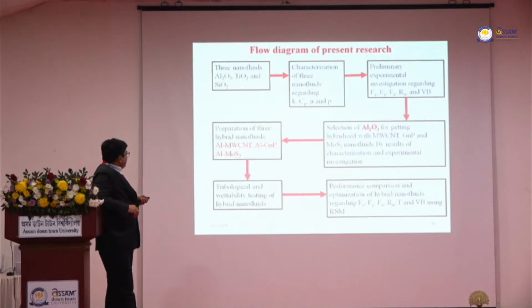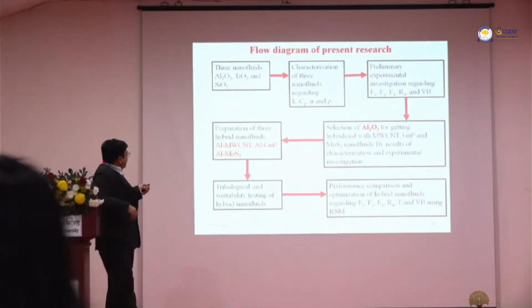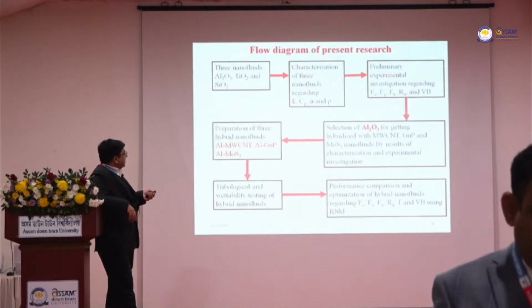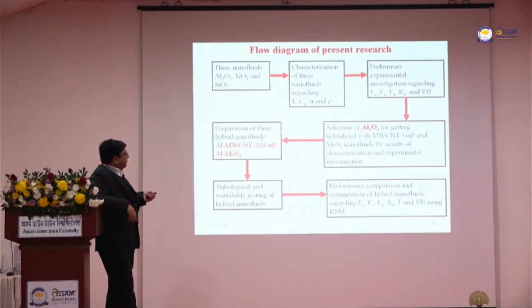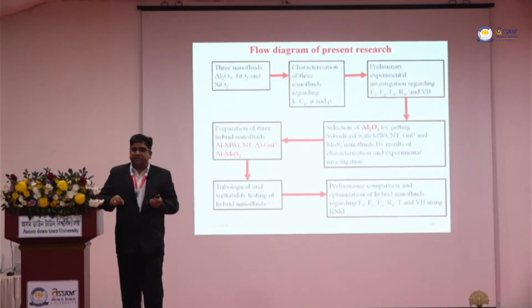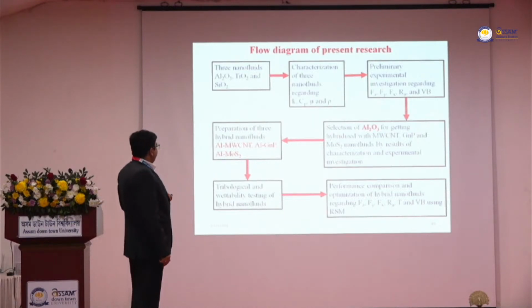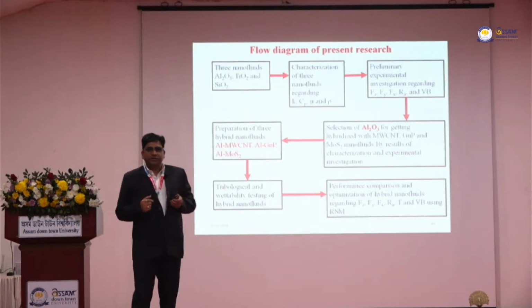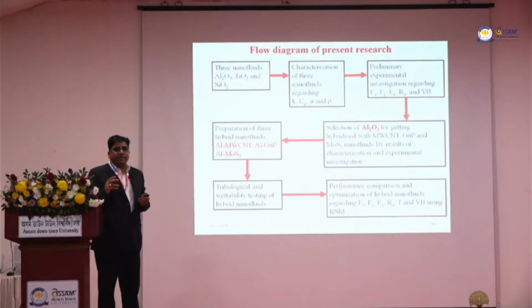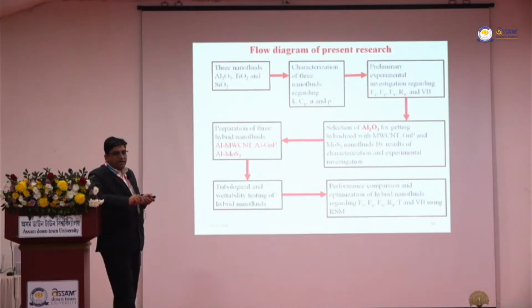Then we did the characterization of the 3 nanofluids: what their properties are, and how their properties are affected by increasing or decreasing the temperature and concentration. Then we did preliminary experimental investigations of how the addition of these nanoparticles into the cutting fluid affects the main response parameters: the 3 components of cutting force, the surface roughness, and the tool wear. After doing this elementary investigation, we found that alumina is one of the best choices out of these 3, and we should try alumina.